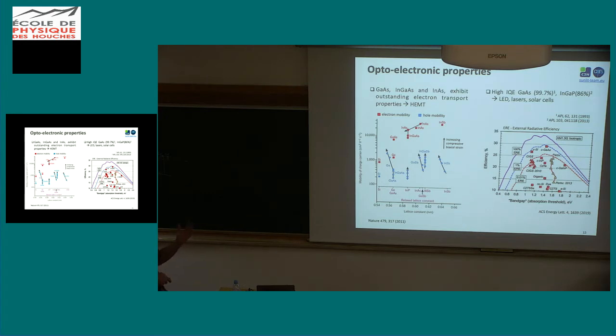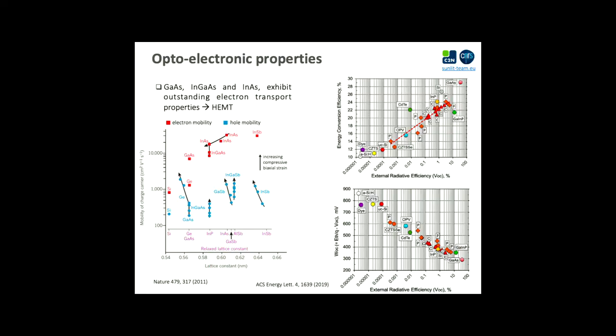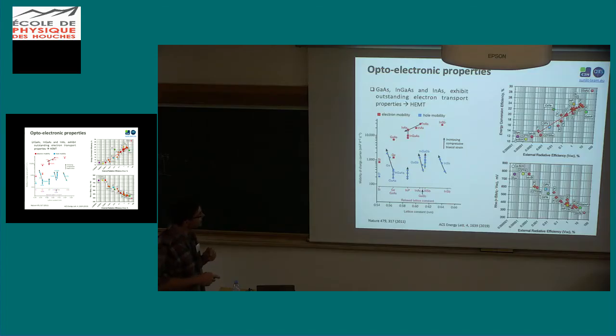This was, if I remember well, the fourth hypothesis in the list of five of Uwe, when you saw that by introducing other recombination mechanisms such as Auger or surface recombination or bulk recombination, then you really reduce the VOC. And another way to see this is with these plots, always from the same paper, where you have the energy conversion efficiency for experimental solar cells with different technologies versus the external radiative efficiency. And you see how, for example, gallium arsenide stands there alone because it features a very high efficiency. This is due to the fact that for such a material, the difference between the band gap and the actual VOC, or splitting of the quasi-Fermi levels, is very reduced for gallium arsenide. This is something, again, that Uwe showed you before.